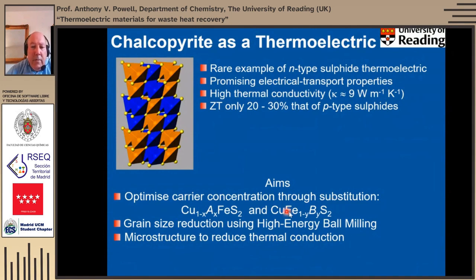So what we've been doing in a very recent project, and this is going on at the moment, in fact, some of this work was presented at the VCT conference this morning, for example. We're trying to optimize the carrier concentrations through substitution either at the copper site or at the iron site in chalcopyrite, and combining that with grain size reduction using high energy ball milling, and also trying to use the microstructure to control the thermal conductivity.